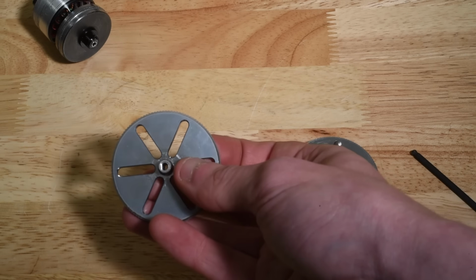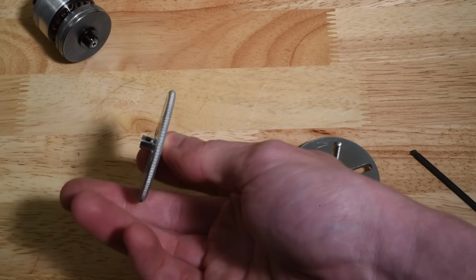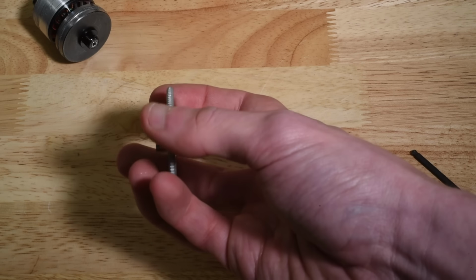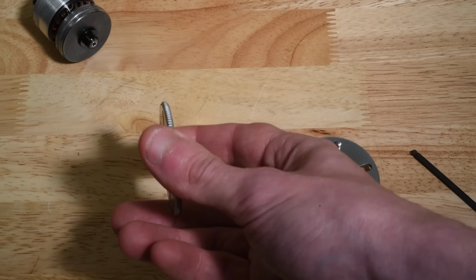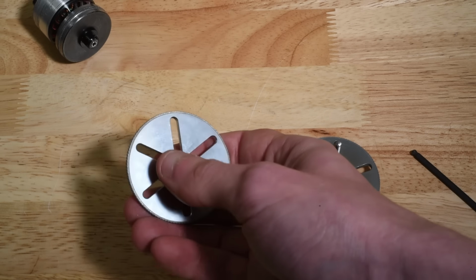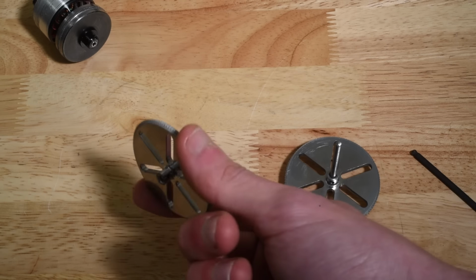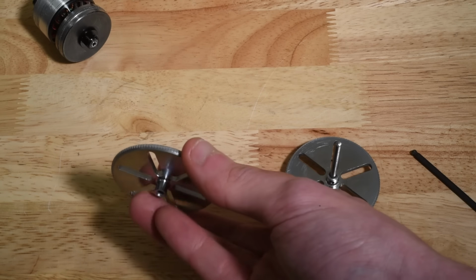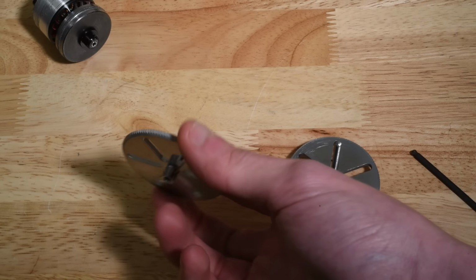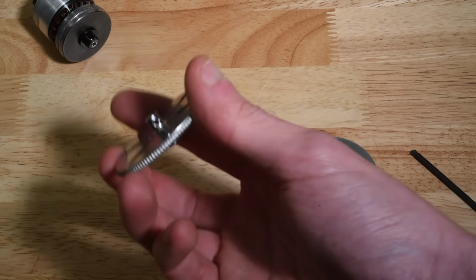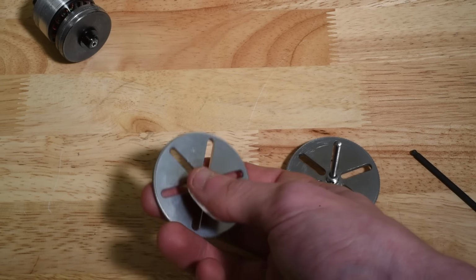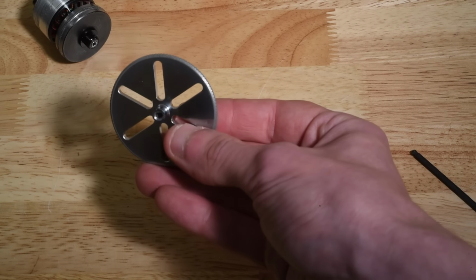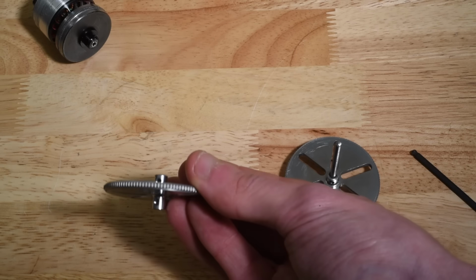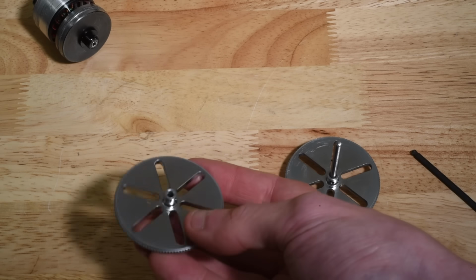We gained more diameter to reduce process forces by increasing the wheel speed. We reduced the edge of the wheel down to 1.5 millimeters, which was the thinnest that PCBWay would make it for us, and we had them chrome plated to reduce the amount of aluminum that would stick to them. The larger diameter helps by making the wheel spin faster. Higher surface speed means lower cutting force, or lower deposition force. Plus, we had it lightweighted and turned to 1 thou tolerance to make it dynamically balanced.